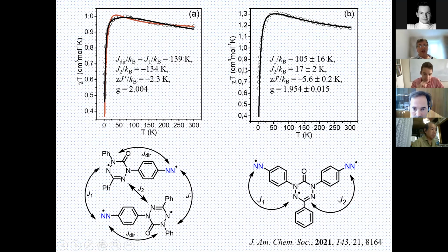If you look at this slide, you will see data of SQUID measurements. For the diradicals, we see domination of ferromagnetic exchange interactions. The same is for triradicals. What was difficult for us was to analyze the magnetic properties of these diradicals, because according to calculations we have a strong enough antiferromagnetic exchange interaction between the diradical molecules. So we have strong exchange interaction inside molecules, and with the same order but opposite sign, we have interaction between the diradical molecules.